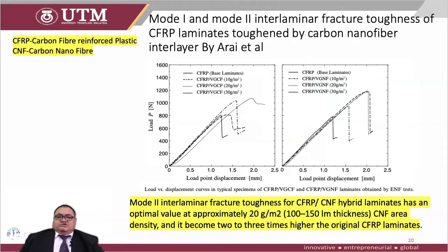For mode 1 and mode 2 interlaminar fracture toughness with carbon nanofiber, this graph shows the effect of density. We can see in the graph that carbon fiber reinforced plastic at 20 gram per meter square has the highest value, 2 or 3 times higher than original carbon fiber. This shows that density affects the load versus displacement.